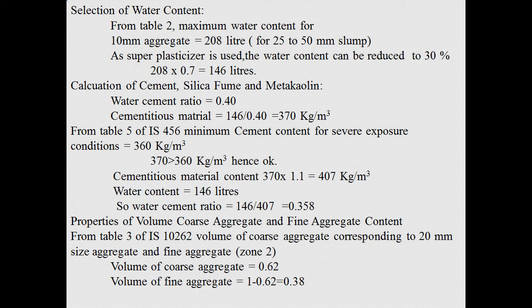146 by 0.4, and a partial factor of safety of 1.1 is used for cementitious material, which gives 407 kg per meter cube. And so the water cement ratio is thus obtained after using Conplast SP430 as a water reducing admixture, which is 0.358.